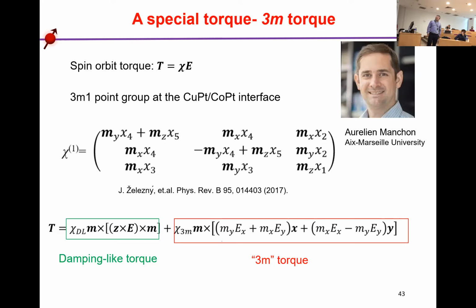Therefore, we have done some analysis based on symmetry, in collaboration with Aurelien Manchon, based on Kubo linear response theory. The torque is linearly proportional to the electric field. When we apply this symmetry to the torque, we can get one damping-like torque and one extra torque. Normally, for common materials, only one torque, the damping-like torque, and the field-like torque is a zeroth-order linear response coefficient.